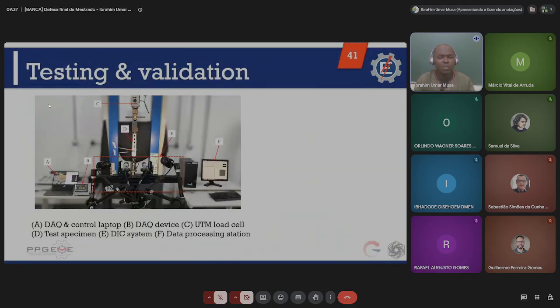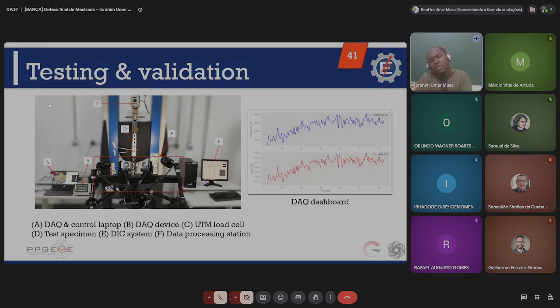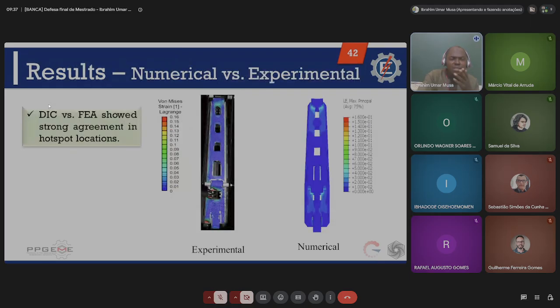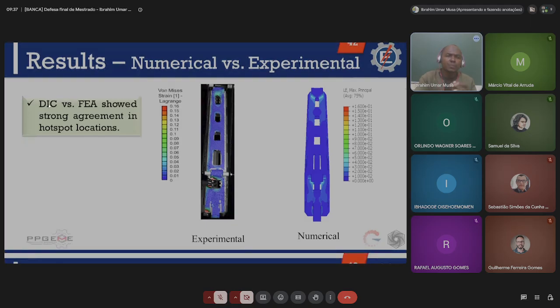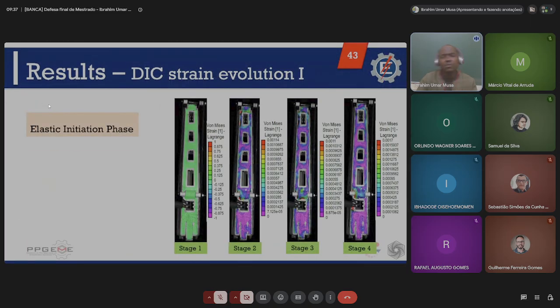And we have the experimental test setup as presented by this image, and a typical dashboard of the data acquisition is also presented by this image. We have, as presented by this image, a comparison between the numerical and the experimental results. We were able to see a strong agreement in the hotspot locations between the experimental and the numerical results.